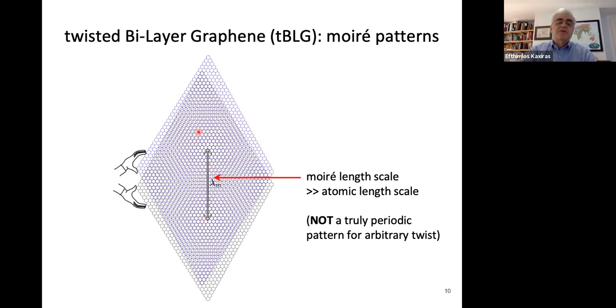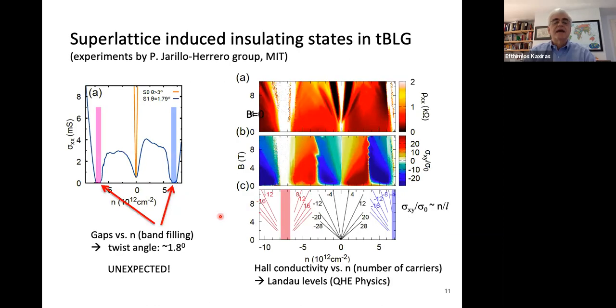So this is an atomistic scale picture of the top layer, and this is the bottom layer, and the combination produces this Moiré pattern at a length scale much larger than the atomic length scale. But I want to emphasize that this is not a periodic structure, and for an arbitrary twist, this is incommensurate type of stacking. And it does produce interesting effects. These are experiments from the group of Pablo Jarillo-Herrero.